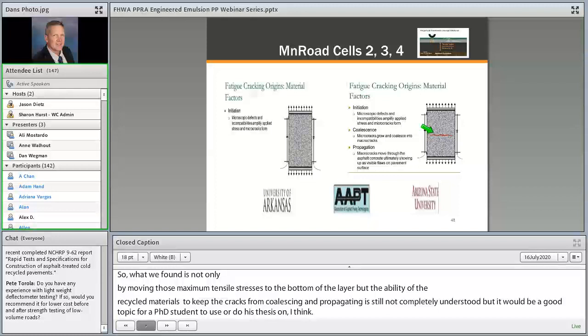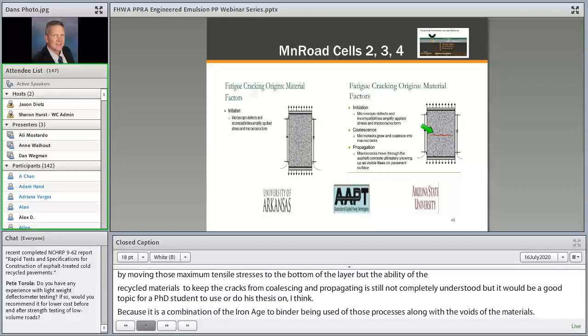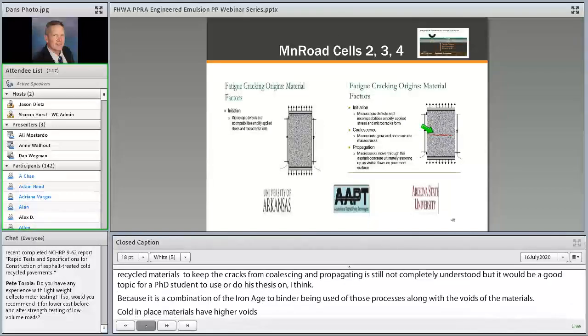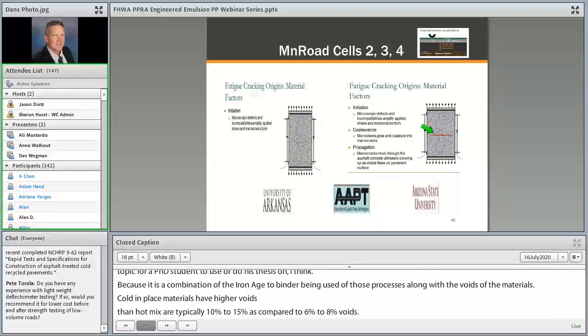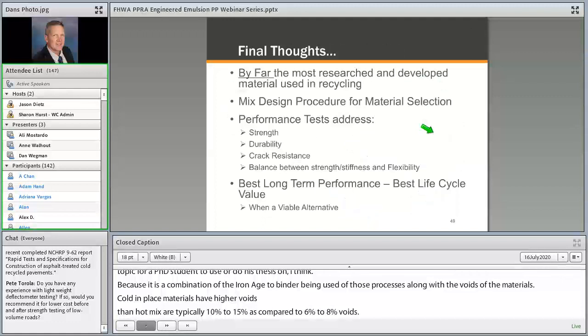Typically, you're looking at 10 to 15% voids as compared to 6 to 8% voids. And I think the whole concept of a crack being able to form and move through that void structure in combination with an unaged asphalt is really key to the ability to withstand that load-related cracking. And so that really gives you an indication of why engineered emulsions perform so well.